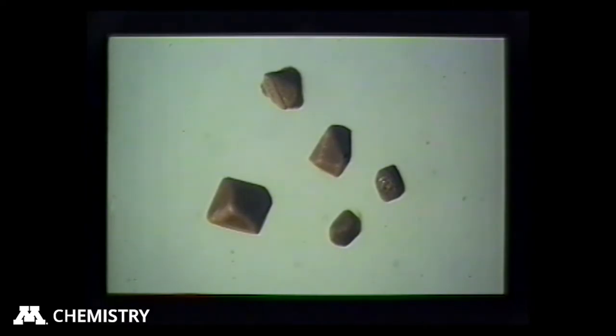So we let those crystals sit for a week or so, and after that time they had turned completely red. And so we think that this change from yellow to red is partly related to the poor quality of some of these colored films that we were looking at. And this is a pure and simple crystal phase transformation, and there's nothing exotic about it. It's a very typical kind of solid state reaction that we see often. And so looking at single crystal components of complex multi-component systems may give you some insight into unusual properties of those more complex systems.